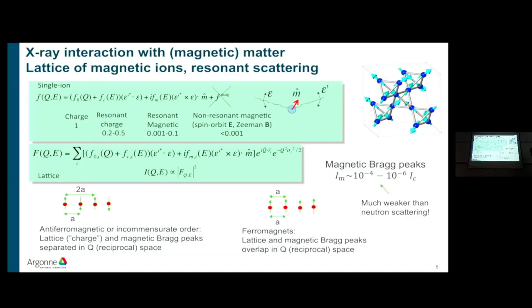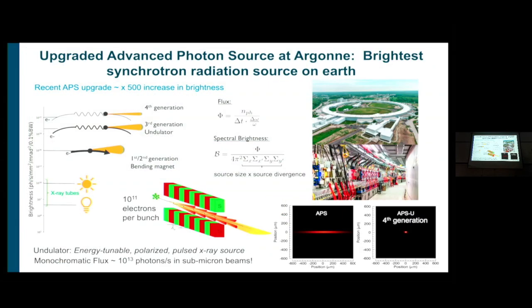So can you not dope the crystal with magnetic substances so the lattice spacing between the magnetic atoms be different from all the atoms? I'm talking about general, antiferromagnets, ferromagnets. You can certainly do things to modify the magnetic structure and cause this commensurate thing to separate. Yeah. But if you have a material that is a ferromagnet and you want to study it, it becomes difficult with this technique.